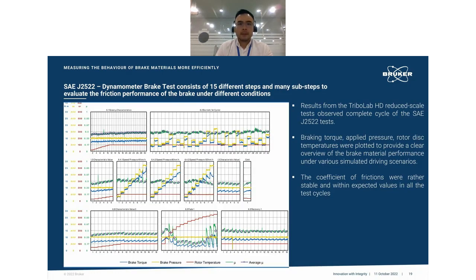So this is an example of all the complete tests that we have done for one particular brake pad. This report is presented similar to what we get from a dynamometer test, consisting of 15 different steps and many sub-steps to evaluate the friction performance of the brake under different conditions. We have the green, the burnish, which is basically the burning in, fade, and of course different speeds and so on.